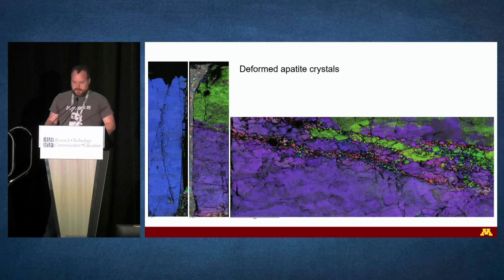The very left-hand image is one side of the crystal, and we see it's all one color, representing that it's a single crystal. On the other side of the sample, we see there are different colors. And this tells us that there were 2 different crystal orientations. And between them, we can see a small band of multiple colors. If we look at the larger zoomed in image, we can see all these little colored grains that have appeared. These are actually recrystallizing grains during deformation of the material. So this is a snapshot of recrystallization happening.